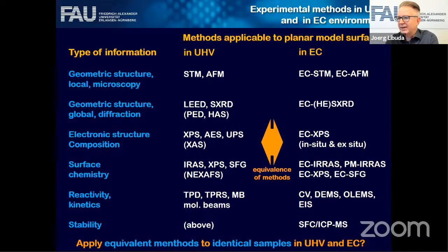For instance, most people use tungsten tips because that's easiest. But tungsten is not very stable. There are many examples where it has been seen that there's dissolution from the tungsten tips, and then you make structures on the surface that are actually dissolved tungsten or derived from dissolved tungsten on the surface, and that happens very easily. And if you change the potential now by doing STS, this is a big problem.